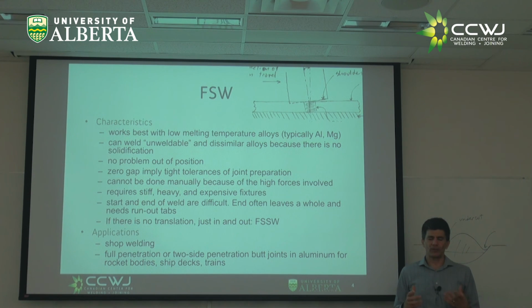It's because some alloys, when they go liquid and then want to solidify, and because all of you took MATI 202, you know that when you go from solid to liquid, you have to go according to a phase diagram. The phase diagram says that the solid will have a composition, but the liquid a different composition. Typically, you end up rejecting solute. That means if you have an aluminum copper alloy, like 2024, which has 4% copper, what goes solid is pretty much pure aluminum, but your liquid is rich in copper. So the next bit that gets solid is pure aluminum and the liquid is richer and richer in copper.